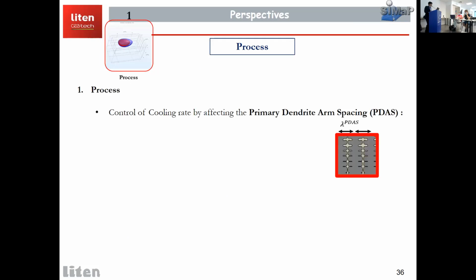So the first one is the processing way. We know that by managing and controlling the cooling rate, we can clearly control the primary dendrite arm spacing, for example. And this can be done by implementing preheatings, for instance, and implementing twin lasers as well. If we are able to put two different lasers into the machine, one which is just preheating the powder and another which is just melting, in this way, we can have a control of cooling rate, and we can have a direct implication on primary dendrite arm spacing. And this might change the cracking tendency.